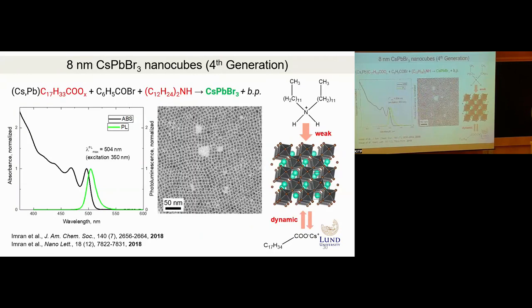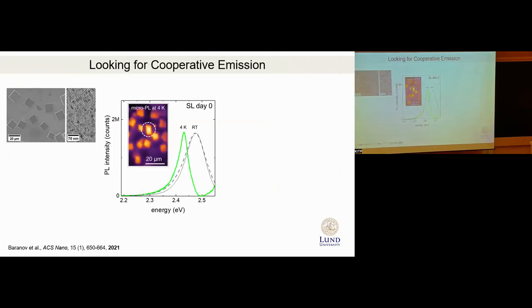So in our efforts at that time, in the Mana group where I was, a new synthesis of nanocubes was developed that produced very uniform nanocubes with very sharp excitonic peaks, by replacing oleylamine with a secondary amine, because oleylamine was binding strongly and contributing to dispersity of shapes. So we decided to work with these nanoparticles in our experiments, and we were looking for cooperative emission in these superlattices. So we cooled it down to 4 kelvins, saw a single peak, and tried to do intensity studies.